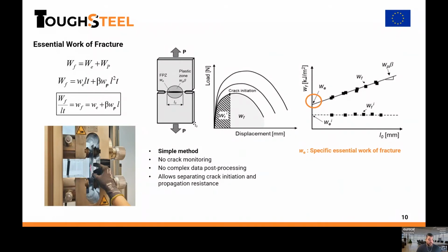The main result, the fracture toughness value that we obtain here, is this specific essential work of fracture, which represents an average crack propagation resistance, since it's obtained from a series of energies for the complete fracture. So it contains contributions from crack initiation and propagation resistance. Although in the literature it is often said that this specific essential work of fracture is equivalent to the JC, the JC value obtained from the J integral procedure, we'll see later that it is not necessarily true.